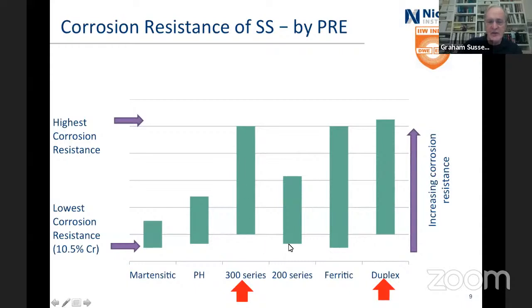The 200 series start lower because there's less chromium in some of them, and stop on the way up. The ferritics go very low. This is absolutely the lowest, the 10.5% chromium of the ferritics, up to super ferritics. And the duplexes can go even further because they put a whole lot of nitrogen, a whole lot of chromium, and a fair bit of molybdenum too, and they get very, very good corrosion resistance. So this gives you an idea of the range of corrosion resistance that you'll get with a duplex and with various other of the alloys. No numbers on it because then you'd wind up getting absolutely bored.